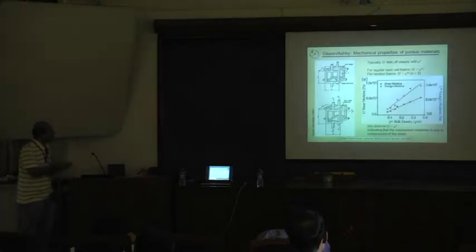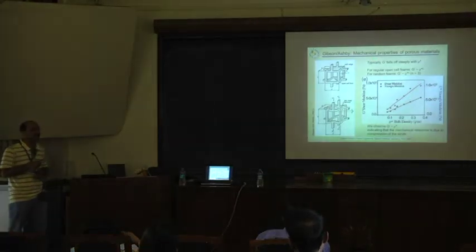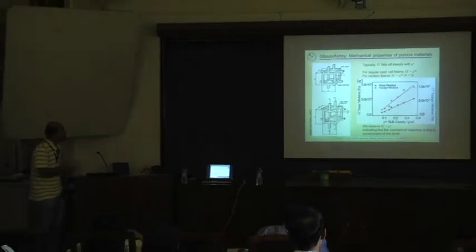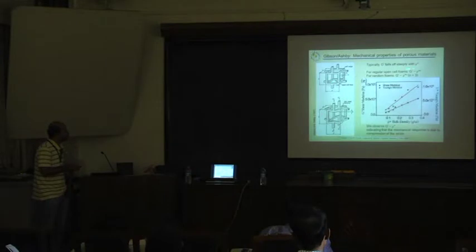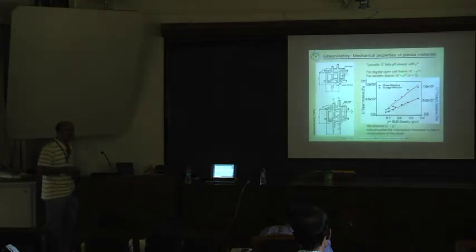Okay. So a slight deviation from the story: when we characterize the mechanical response of these materials, there's a lot of work known on porous structures in idealized situations where you can form these strut-like assemblies. One of the things you notice is that as you decrease the amount of material that goes into the walls, the modulus decreases. Typically for regular open cell foams, you can do a calculation for how these struts will buckle, and that gives you a decrease in the modulus that goes with the square of the density. So as you go to lower densities, the modulus falls off quite a bit.